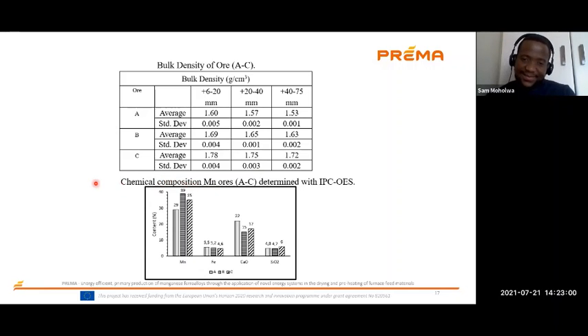This here is the chemical composition of the ore that we used in this study. We have A, B, and C. You can see we are reporting the manganese content of this ore. Here is the iron, the calcium oxide, and the silica oxide. You can see that B has the highest content of manganese at 39%. We have iron content being the highest in OA by 5.5, and we have calcium oxide being the highest in OA. Then we have the silica dioxide being the highest in OC.